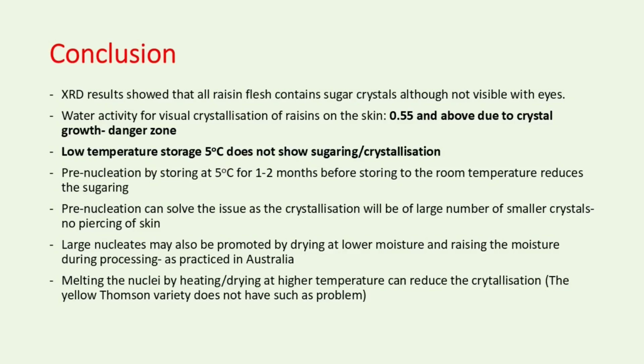And then one of the experiments was done in Chile, on melting, because all of the dried grapes will have some very small crystals. But if you can melt those nuclei by heating to 60-70 degrees Celsius, that is happening in Chile in the process. Certain varieties, they do that, not all varieties. If you can melt the nuclei by drying at very high temperature initially, that melts the nuclei, and that avoids the problem as well. So we could see the mechanism as well as how you resolve the problem.